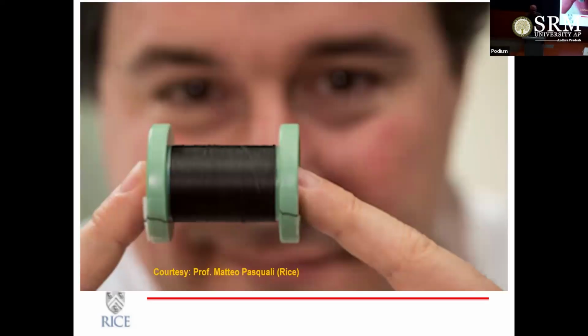Now, when the carbon nanotubes were discovered in the early 1990s, 1991 to be precise, people thought they had discovered the strongest fiber. And every theoretical calculation about this nanotube structure, a perfect structure made of this hexagonal honeycomb carbon lattice, that is the graphene structure, rolled up into a cylinder, said that this is the ultimate fiber, right? You have the highest mechanical strength, you have the highest electrical conductivity. So the question was, how do you really translate this beautiful building block, a small tube that is almost as perfect as you can get with no defects, into a practically relevant material, right? That kind of is the context in this whole nano engineering talk that I'm going to give.